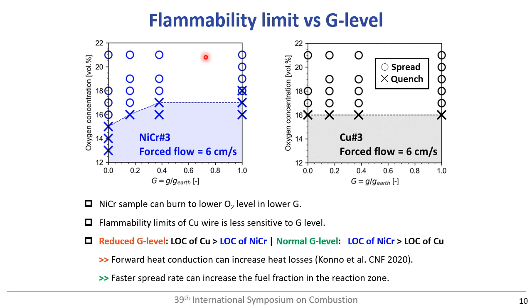So this slide shows the flammability limit as a function of gravity level. The results for nichrome and copper cases are presented. In the figure, circle and cross symbols correspond to flammable and not flammable conditions, and this dotted line is the approximated flammability boundary. In the previous slide, I explained the spread rate as a function of gravity level, and the spread rate was suppressed under lower gravity conditions. But interestingly, the flammability boundary is expanded under lower gravity conditions for the nichrome case, but the flammability boundary for the copper sample is less affected by the gravity level.